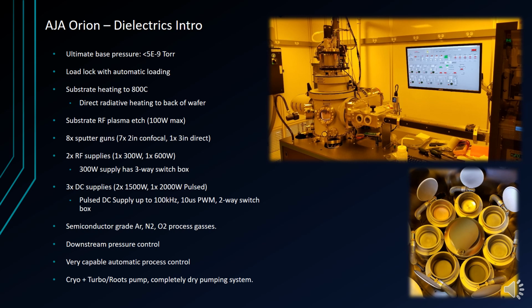There are 8 sputter guns, where 7 are 2-inch cathodes confocally oriented at an angle toward the substrate for uniformity across 6 inches with rotation. There is one 3-inch centrally located gun which faces directly at the substrate. This gun is not uniform over the entire wafer, but rather is only uniform at about 2-inch diameter relative to the center of the holder.